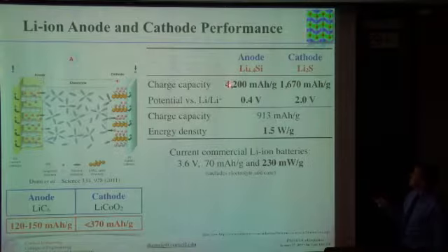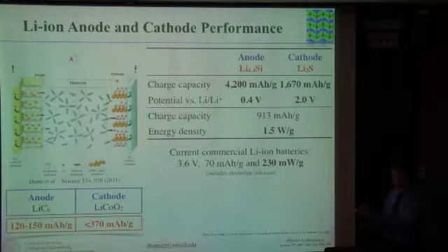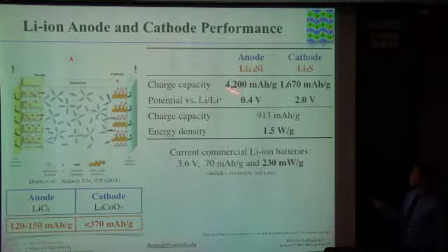And so if you go through the numbers, lithium silicon and lithium sulfur, the capacities, remember for current batteries, like in the laptop here, they're of the order few hundred. We're now in the order 1,000. We combine them. Here's their voltages. We end up with a voltage of 1.6 volt in that case. We end up with a combined charge capacity of 900 and an energy density of 1.5 watt per gram.